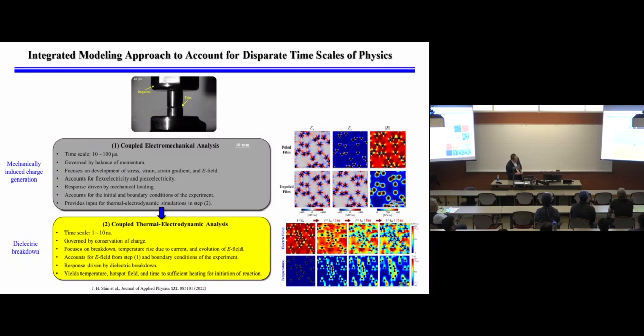Electricity. Unpolled has only flexo. So it gives us a way to separate those two, right? So we have all those. And under mechanical loading, you first develop the E-field. As you can see, the E-field is heavily concentrated around the particles because that's where you have high stress and high strain gradient. Then when the E-field is strong enough at some point, you have dielectric breakdown.